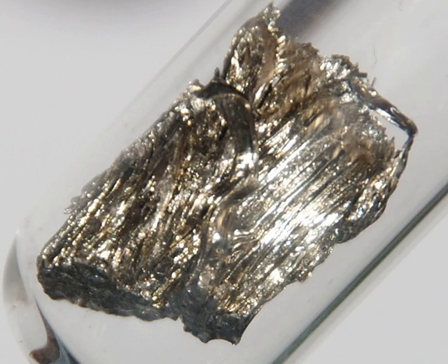Chalcogenides. Samarium forms trivalent sulfide, selenide and telluride. Divalent chalcogenides SmS, SmSe and SmTe with cubic rock salt crystal structure are also known. They are remarkable by converting from semiconducting to metallic state at room temperature upon application of pressure. Whereas the transition is continuous and occurs at about 20 to 30 kilobars in SmSe and SmTe, it is abrupt in SmS and requires only 6.5 kilobars.